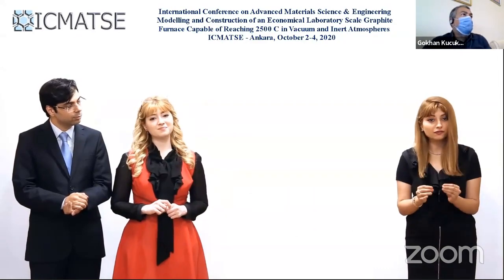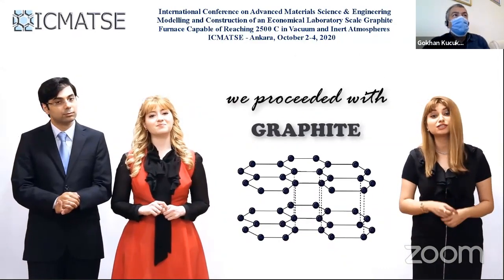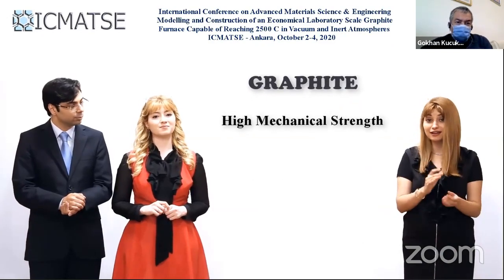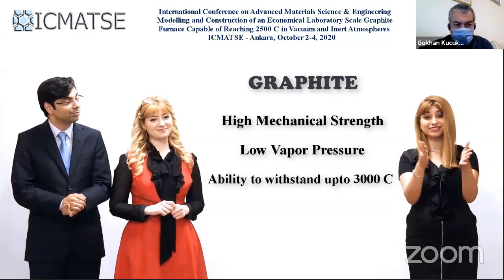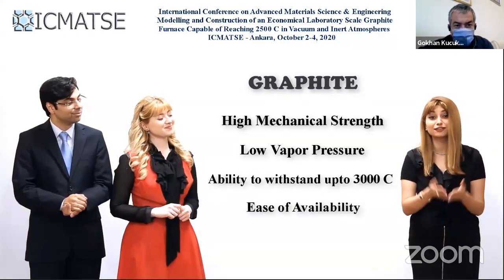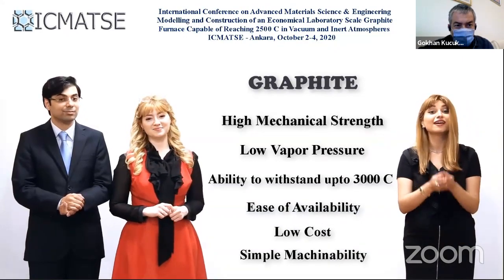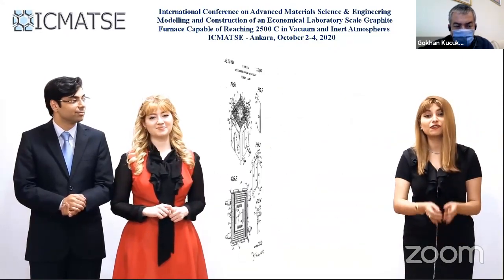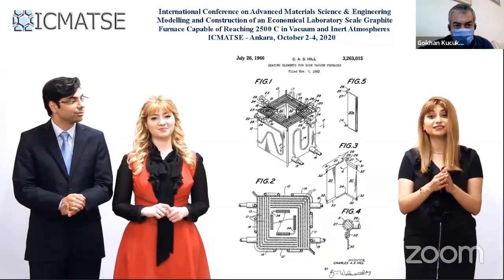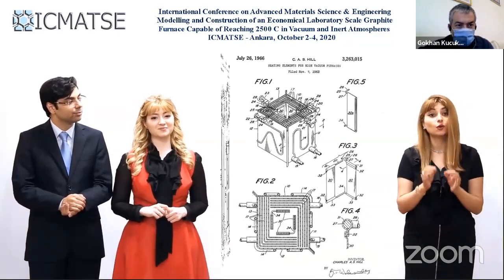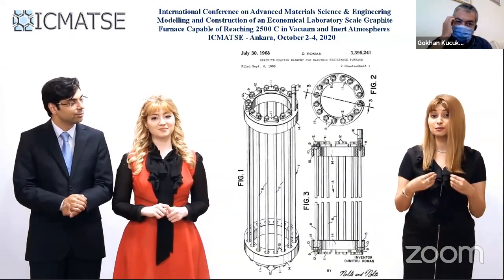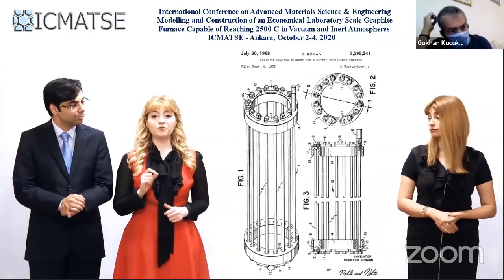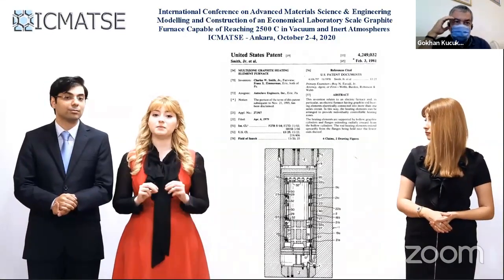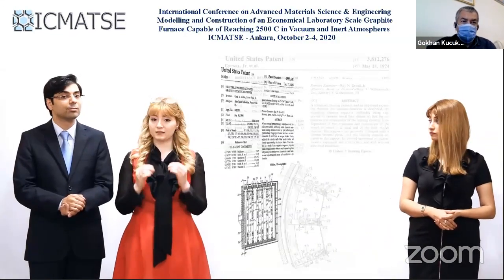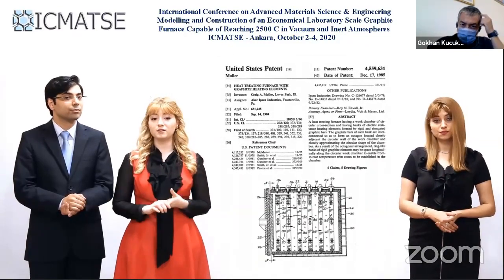Therefore, we proceeded with graphite due to its impressively high mechanical strength at high temperatures, low vapor pressure, ability to withstand temperatures up to 3,000 degrees Celsius, ease of availability, low cost, and rather simple machinability. There are very interesting graphite hot zone designs either published in academic literature or patented, some of which are widely used industrially. However, upon reviewing them in detail, we found that there are only a limited number of hot zone designs available that meet the requirements of a compact lab-scale graphite furnace for research and development purposes.